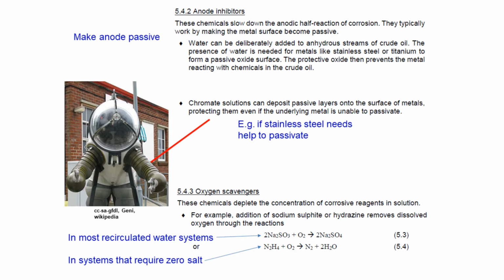Another way, also called an anode inhibitor, is that you might add chromate solutions, spiking them into your process stream. This is only possible for certain kinds of streams, not anything you need to keep absolutely pure, and maybe this would be into a recirculated water system where it's not going to be lost and poison the environment. We might promote passivation this way. If we had a stainless steel which was not quite as passive as needed, maybe we'd chosen an alloy with too low a chromium percentage, then we could add chromate solutions to the stream passing over and causing corrosion of the stainless steel, and they would promote the formation of the passive layer. Again, that would be called an anode inhibitor.